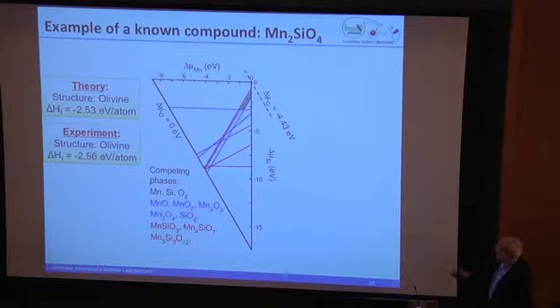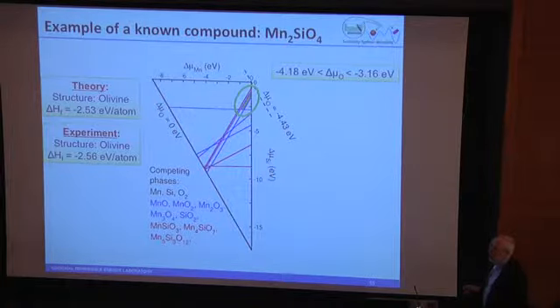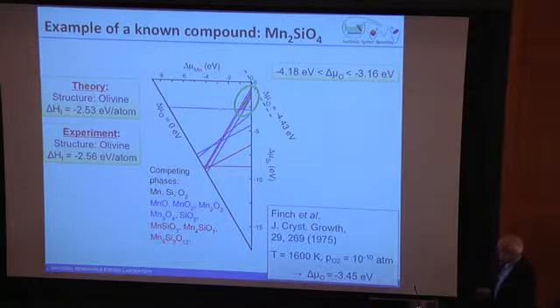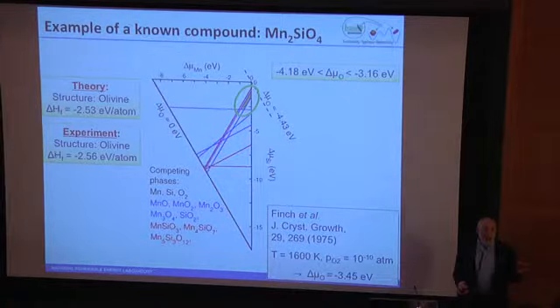And so, again, you can look at all the competing phases. This tells you that in this range for the chemical potential of oxygen, you ought to be able to get this phase. It's a pretty narrow synthesis range, actually. Interestingly enough, when you look at the literature, the only place they get this is right in that range. So now we have a connection between theory and synthesis, telling us where we can make something. Now, that doesn't tell you anything about the kinetics, which is hopefully something we'll get to, but at least tells you that in this range, it ought to be thermodynamically stable.